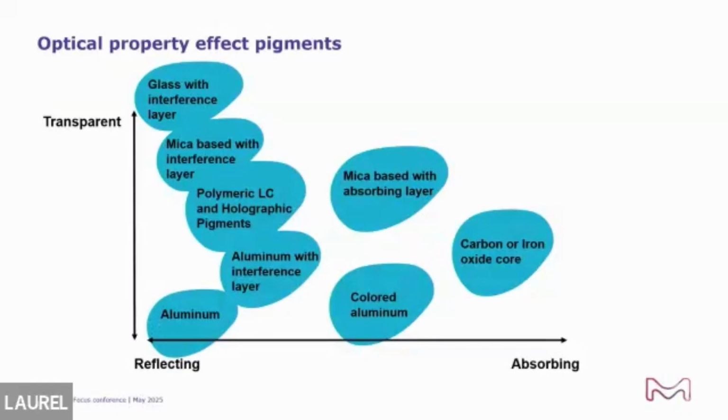At the corner, that's your aluminum. It's highly reflective and less transparent. If we go up all the way, that would be your glass flake pearl pigments. I know glass flake is used in automotive, and is starting to be used more. They're highly transparent, but they have much less hiding. There's almost no hiding. So anything else is set in between.